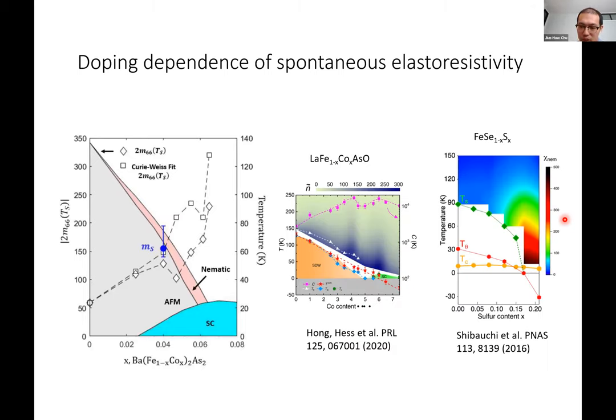There's no magnetic phase. We haven't tried that, but I know Cliff Hicks has already tried that, and the rumor is that it's not changing a lot. You can also infer that from Anna Böhmer's measurements, where they measure how the orthorhombicity changes when you enter Tc. For cobalt-doped barium 122, the orthorhombicity decreases a lot when you enter the superconducting state. But for iron selenide, the orthorhombicity almost doesn't change when you go across Tc. So that already implies that there won't be a lot of suppression, because this is basically a thermodynamic relationship that works both ways, right? But again, that's just pure iron selenide. I don't know what will happen here, and to my knowledge, no one has actually measured here.